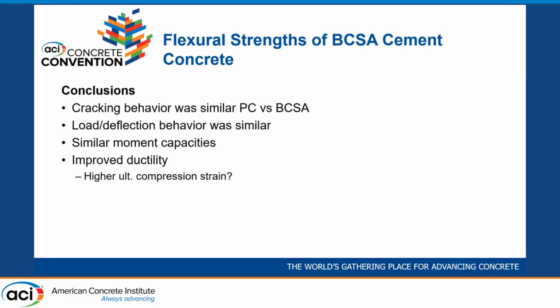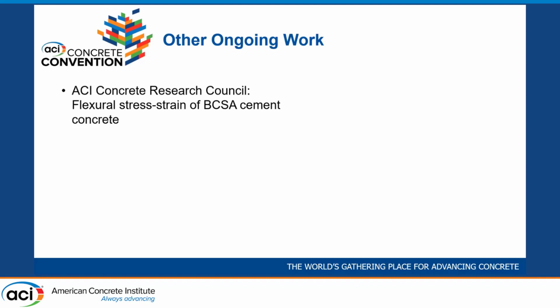So we found that cracking behavior was very similar between the Portland cement and BCSA cement beams. The load deflection behavior was similar. The moment capacities were similar, but we actually had this improved ductility that potentially points to a higher ultimate compression strain. So what we've been working on now, we were fortunate enough to receive a Concrete Research Council project to look into this ultimate compression strain issue, look into the stress strain distribution for this cement.